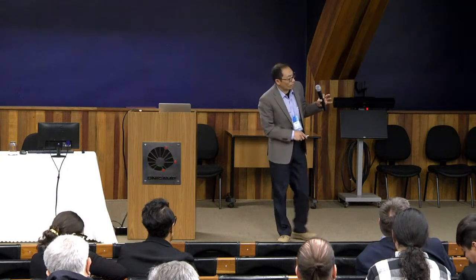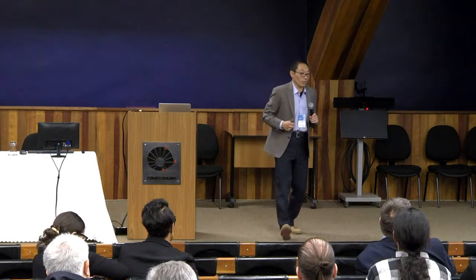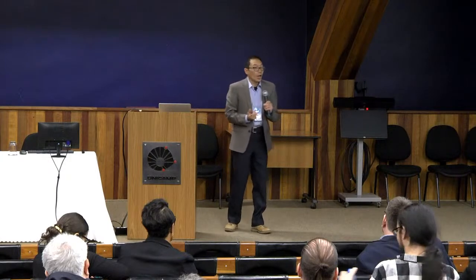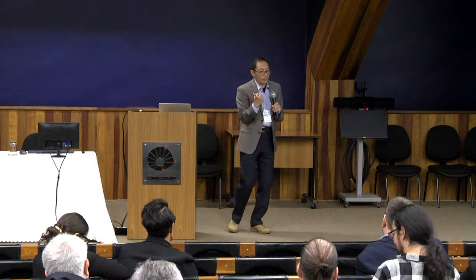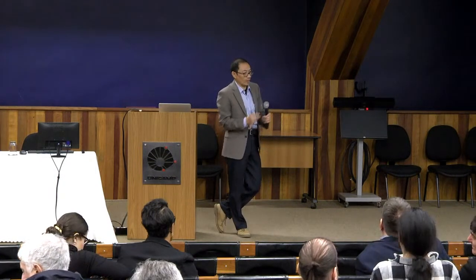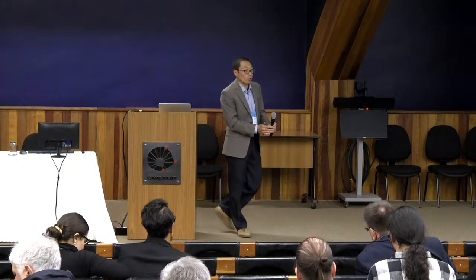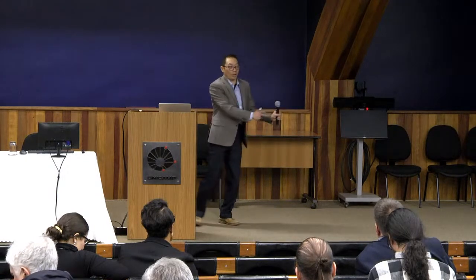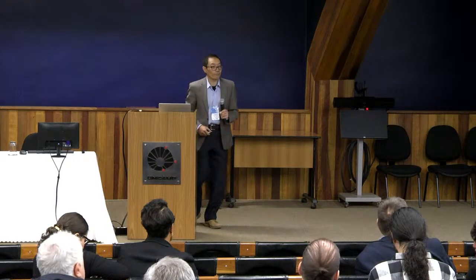And oxygen, I didn't show those ex situ oxygen results, sorry. I didn't show the oxygen because oxygen with in situ is another disaster. We always see other very strong oxygen signatures from the electrolyte, and in the typical example, oxygen is everywhere. The change of the oxygen turned out to be a radiation damage effect, so I didn't show it here. I think in situ experiments are critical for many surface and interface related phenomena, as you've heard in talks on those. In the battery compound, most of the cases we actually prefer the ex situ experiment. It is much cleaner, and the analysis is much more reliable compared with the in situ test. Not all of them, it's really case by case, but that's roughly how we form this in situ cell.